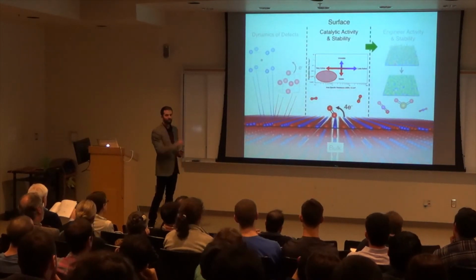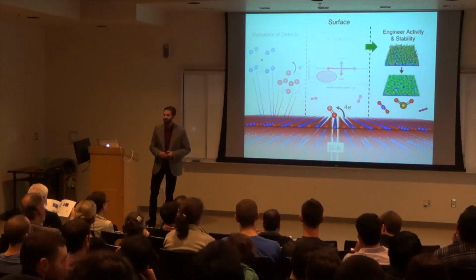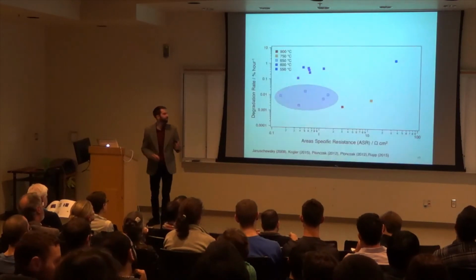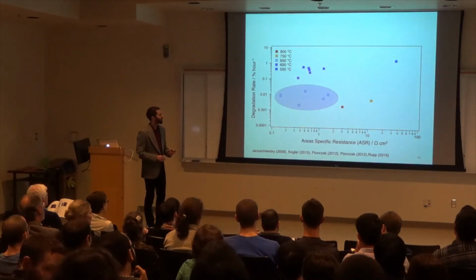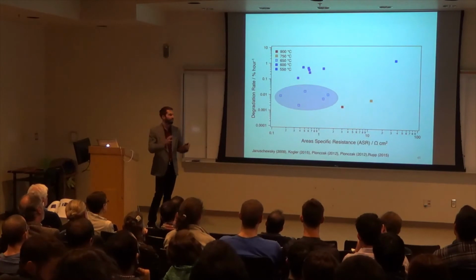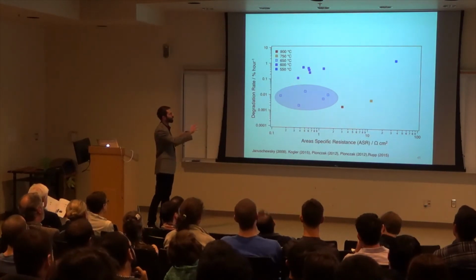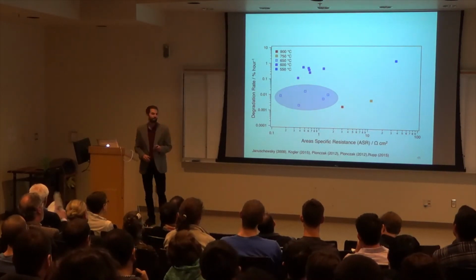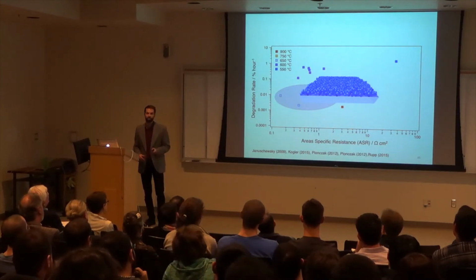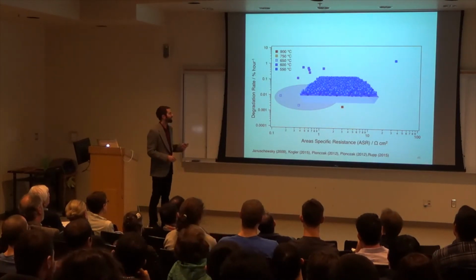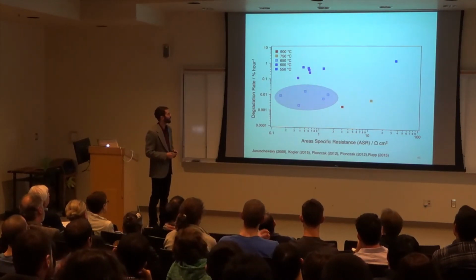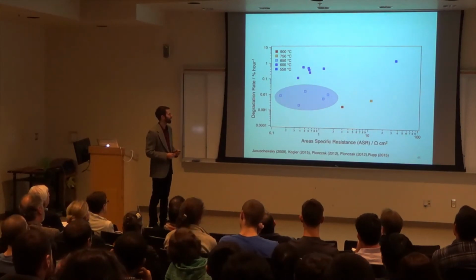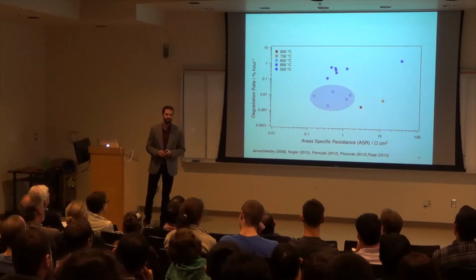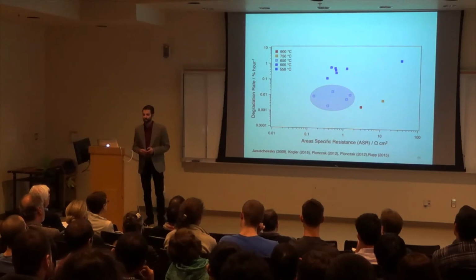And so now we're talking about what we can do about this situation. Essentially taking what we've learned in the first 2 sections and trying to engineer a more active surface. So to do this, we're going to hit our material systems up against the porous structure, something that has a higher surface area. And to do that, we actually need to shift the scrap over to an even more active surface regime, catalyst regime.